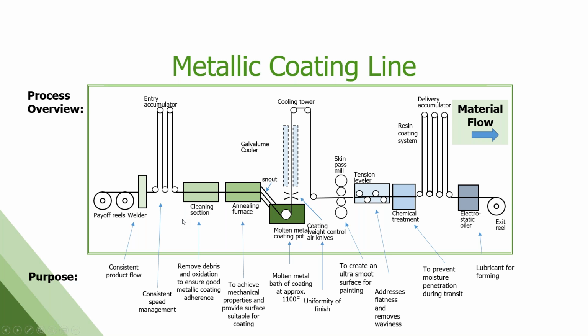So these lines are run about 150 feet per minute and faster, up to 700-800 feet a minute these days on the newer lines, and they hold on average anywhere from 2,500 to 5,000 linear feet of steel from end to end. It's a very large operation, lots of material at once being processed.